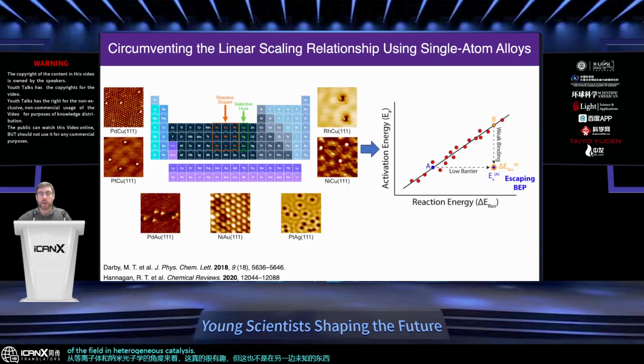So this is a large area of research for many, many groups around the world, because as you dope in small amounts of dopant metals, so reactive dopants could be something from the iron group, iron, cobalt, or nickel, or the platinum group, ruthenium, rhodium, palladium, osmium, iridium, platinum, so on and so forth, with these selective host metals, copper, silver, and gold, which happen to be the plasmonic metals that we think about quite a bit. As you dope these in, you can do something called break a linear scaling relationship.